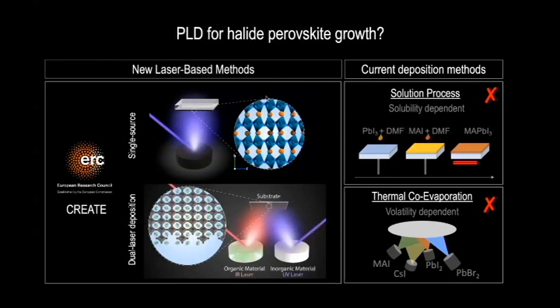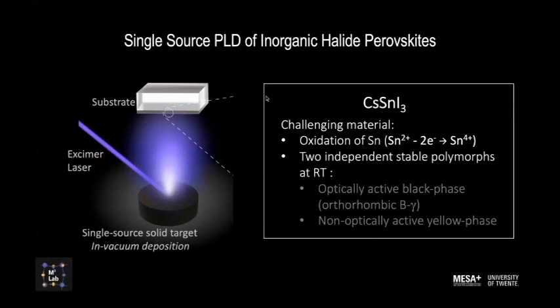Actually, she already did a lot on the single source growth, and a system that is capable of doing this dual laser deposition is being made at this very moment. So hopefully we can show some results on this soon. But just to show some work on the single source deposition of this inorganic halide perovskite, in this case cesium tin iodide, this is a quite challenging material because you need to control the oxidation of the tin, but you also should be able to stabilize the right polymorphs, and this should be done at room temperature.